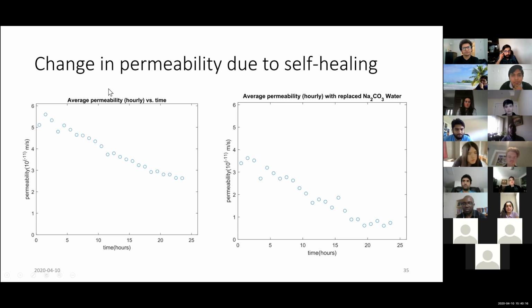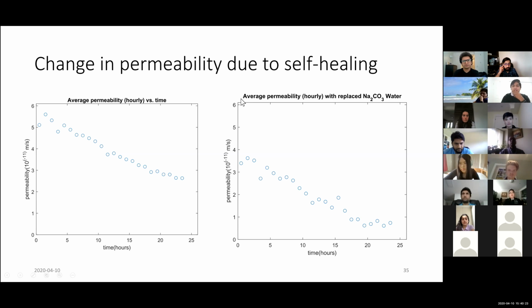So this is now the test that I did to completion. What I observed was, this is the first 24 hours of handling the sample. We have water inside the system which permeates through, and this is the average permeability with time. This decreases first faster and then a little bit slower, and this is due to continued hydration happening inside the system, so the permeability is decreasing. So this is the first 24 hours.